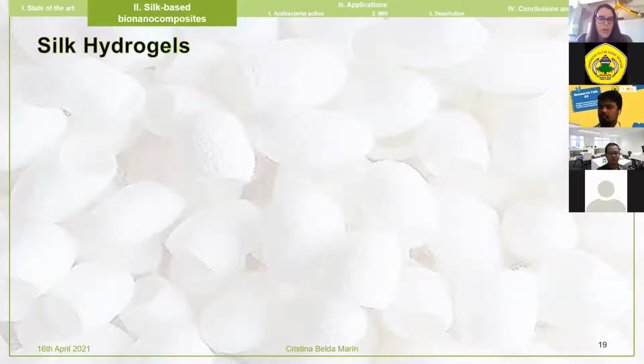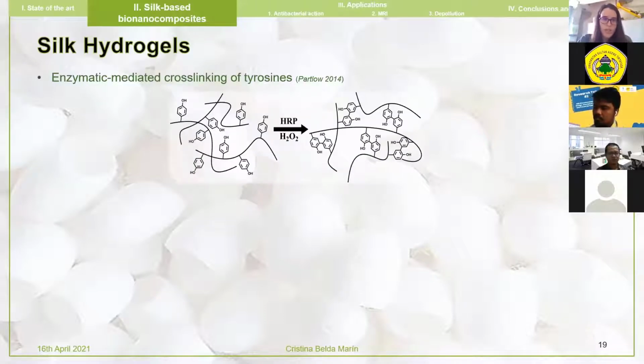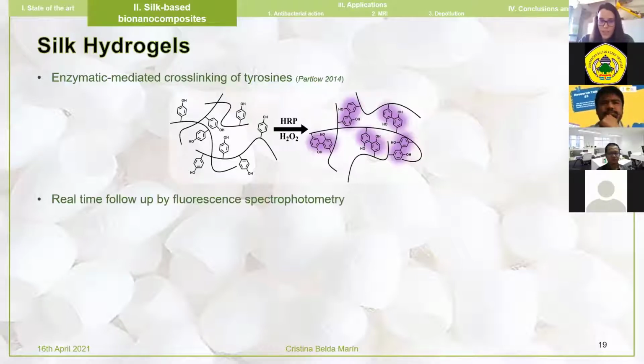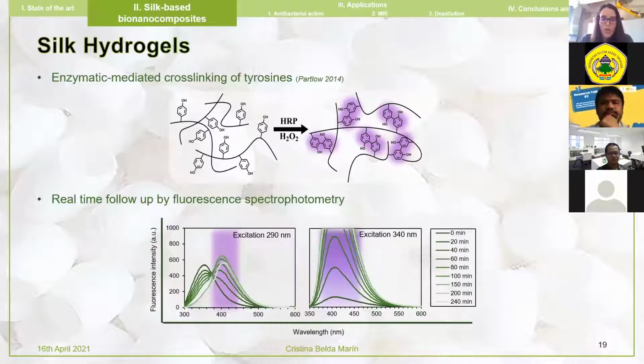So I'm going to explain now something about the silk hydrogels, the materials that we have been focused on. Silk hydrogels can be produced by enzymatic cross-linking methods in which we are using horseradish peroxidase to induce a cross-linking of the tyrosines found within the silk structure. And these tyrosines form a dityrosine bond, which is then fluorescent. So this allows follow-up of this hydrogel formation through the appearance of this fluorescence peak.